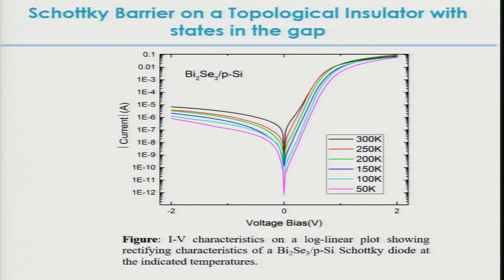However, this is not a good topological insulator. So our goal now is to get, in other words, the Fermi energy cuts through the conduction band here. So when you analyze this, we're not looking at just the surface state on our counter electrode, but we're looking into the bulk. But it is a very nice Schottky junction.